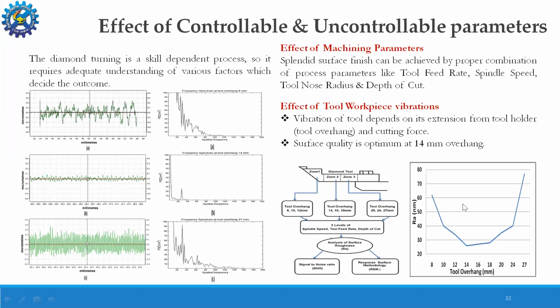So surface quality is improving. And when the overhang increases from 14 to 27, the roughness started increasing. So we found that the surface quality is optimum at 14 mm overhang, and this can further be seen by the power spectral density, that is the frequency spectrum obtained at different overhang.